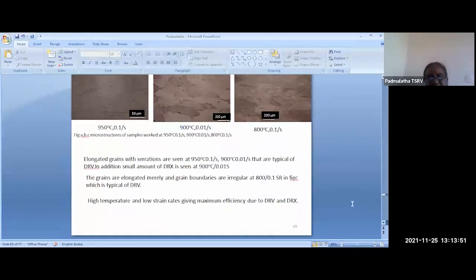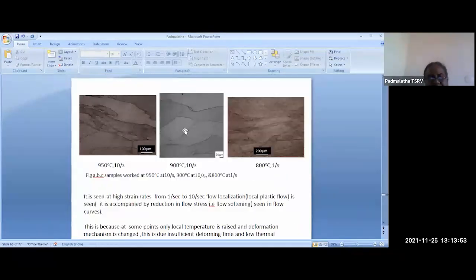Here we can see the flow localization is happening here and here, due to which the flow softening is taking place. But this flow localization is not good for us, because it has happened only in certain regions, not the entire region. That means it is an instability. And instability always tells us it is not a safe zone. We should avoid these zones.